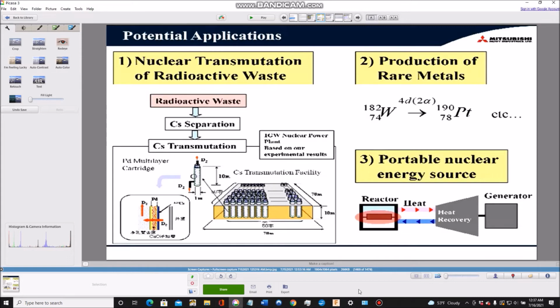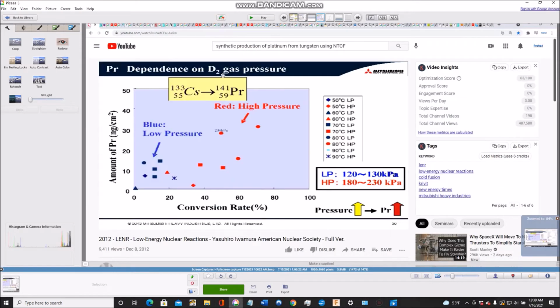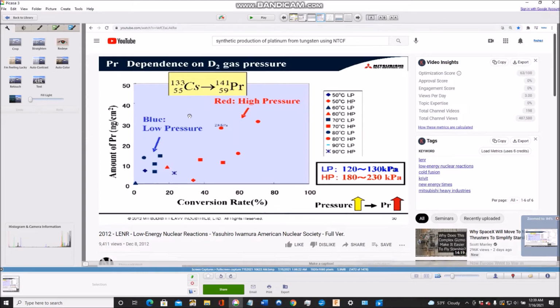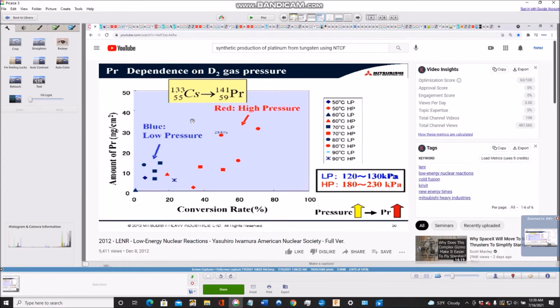be achieved. So here you can see the pressure versus conversion rate, and that's for cesium into praseodymium. You can see at higher pressures you're getting a higher conversion rate. So they're getting about 70% conversion at 230 kilopascal, and so it is possible to, again, process intensify this reaction,